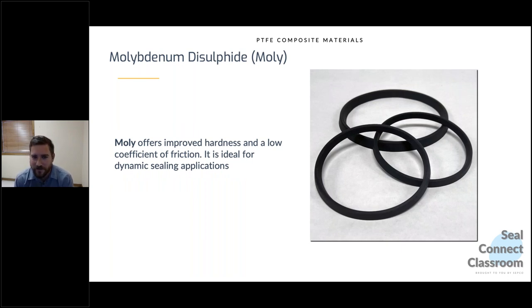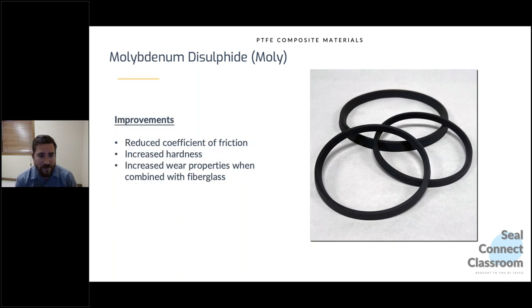The best friend of fiberglass material is molybdenum disulfide, commonly called moly. It's the tag team. It's almost always the two work together. You hardly see moly without fiberglass, even though sometimes you see fiberglass without moly. But moly improves hardness. It lowers the coefficient of friction, so it increases that wear performance, whereas you add the fiberglass for strength. Now you get the moly coming in that adds some lubricity, adds some lower coefficient of friction. So it's ideal for those dynamic sealing applications, which we'll talk about on the next slide.